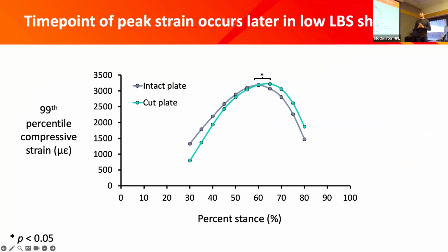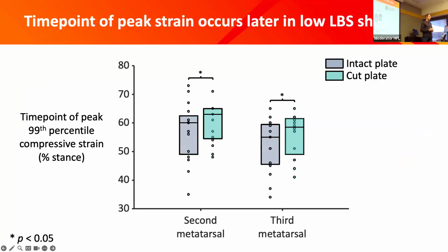We also saw that the time point of peak strain occurred later in that lower longitudinal bending stiffness shoe, the cut plate shoe. So this is a representative subject here, just looking at the time series data of the strains there. And the peak strain here occurs significantly later than the peak strain in the intact plate shoe. And if we just plot that in box plot form, we can see that for both the second and third metatarsal, that time point of peak strain occurs later in the cut plate shoe. So there's something happening there with the timing, and there's something happening there with the force that's just not translating to a change in the actual strain metric.